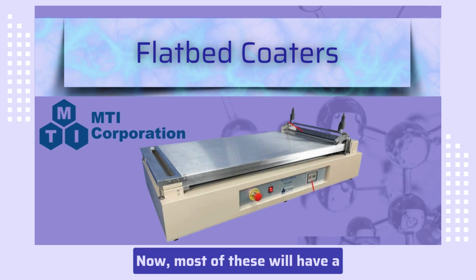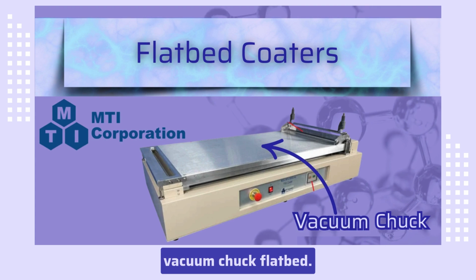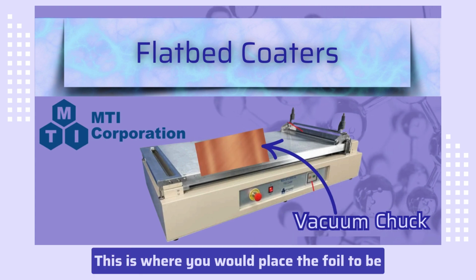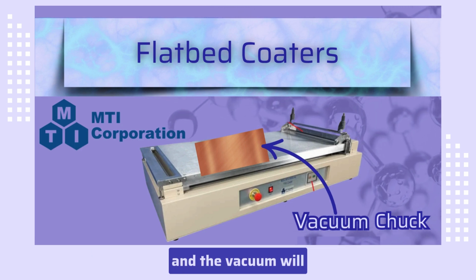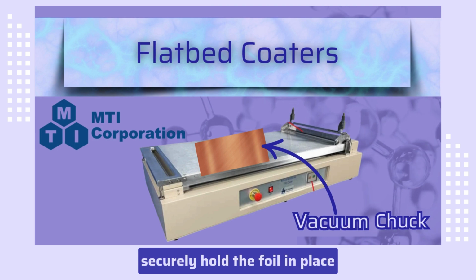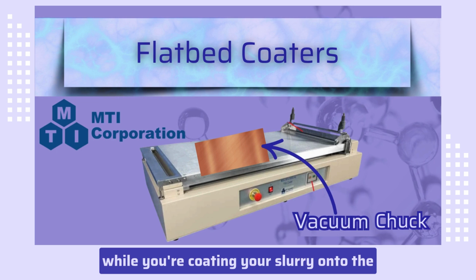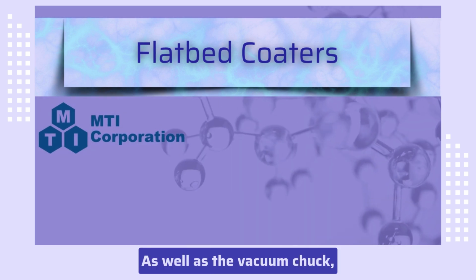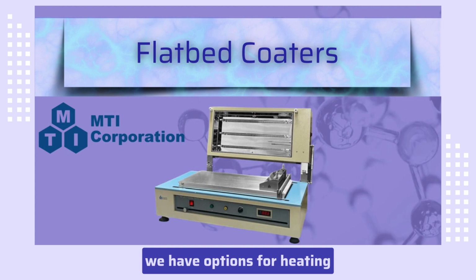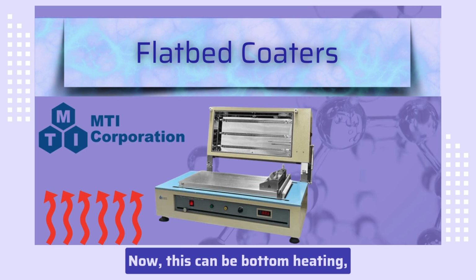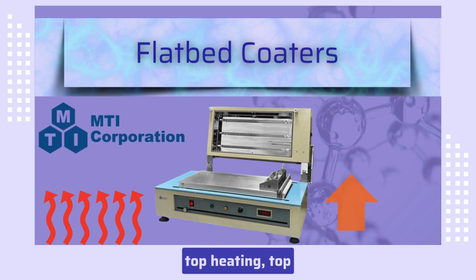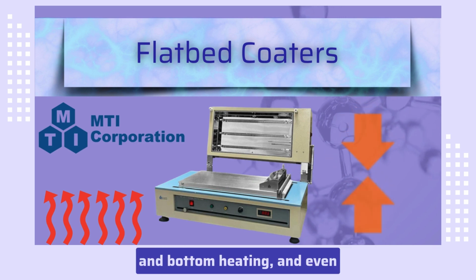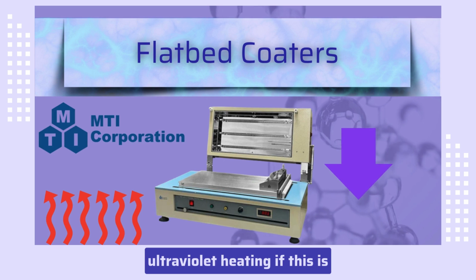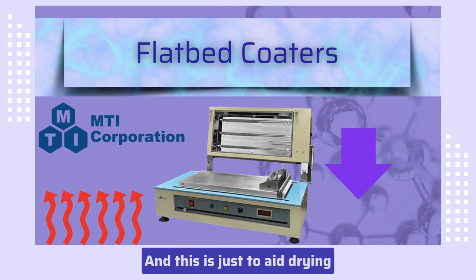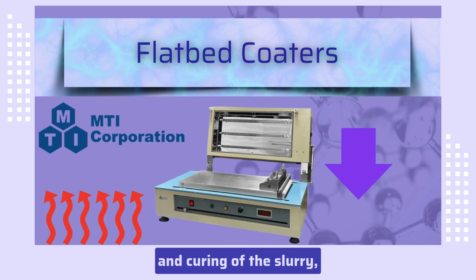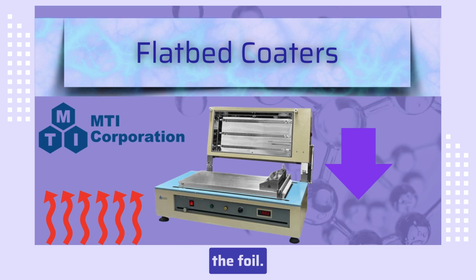Now, most of these will have a vacuum chuck flatbed. This is where you would place the foil to be coated onto, and the vacuum will securely hold the foil in place while you're coating your slurry onto the foil. As well as the vacuum chuck, we have options for heating as well. Now, this can be bottom heating, top and bottom heating, and even ultraviolet heating if this is required. And this is just to aid drying and curing of the slurry once it is coated onto the foil.